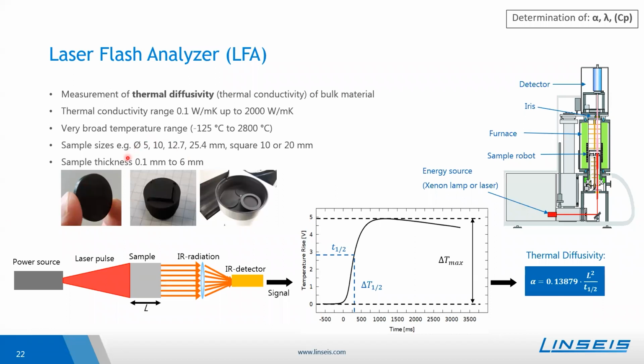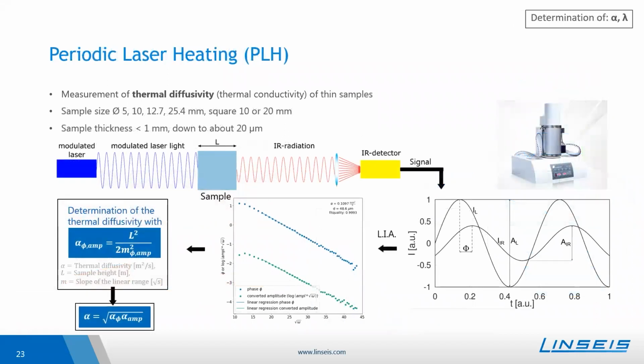I mentioned that the sample thickness can go down to about 0.1 millimeter. If one has a material with a lower thickness, one can, for example, use the periodic laser heating, shortly PLH. This is a new technique with a brand new instrument we offer. It is especially useful for thin samples, lower than 1 millimeter, maybe down to about 20 micrometer thickness, to be able to determine the thermal diffusivity. Sample size and sample preparation are similar to the LFA technique. Also, the general setup is similar, as you can see here.